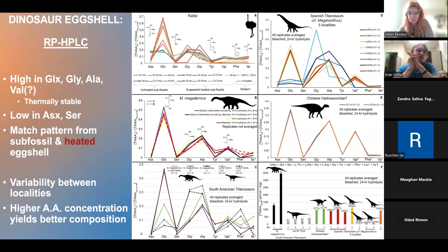But what's really exciting is when you do the high-performance liquid chromatography to characterize the amino acids in some of these dinosaur eggshells. So if you look at, say, some of these titanosaurs in panel B or the Chinese hadrosaurids in panel E, you can see that there is a profile of amino acid composition that is very exciting. You have high glutamic acid, high glycine, alanine, and valine, possibly valine. And those are really the only amino acids that consistently come out across all of our replicates. They are depleted in aspartic acid and serine. And this is the exact pattern that you would expect from subfossil avian eggshell, as well as avian eggshell that's been heated either naturally or experimentally.